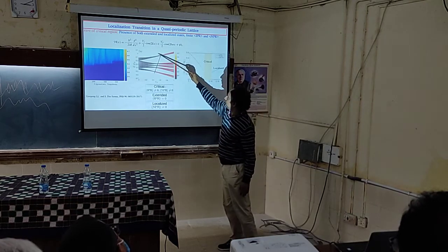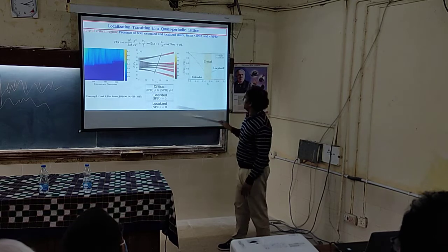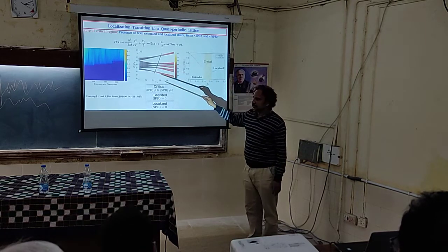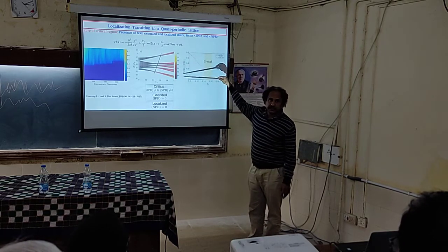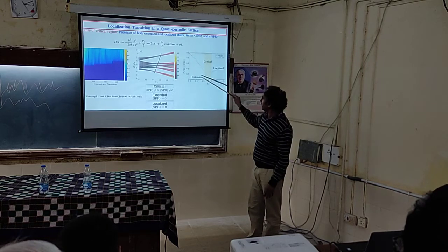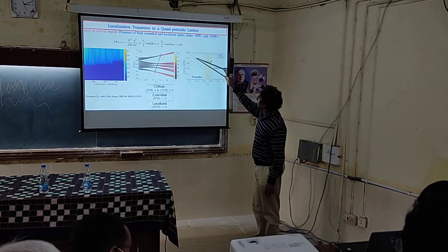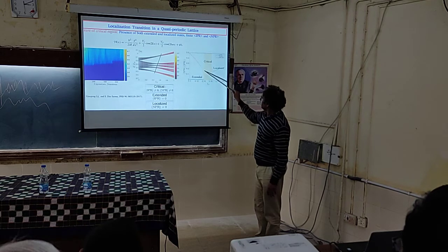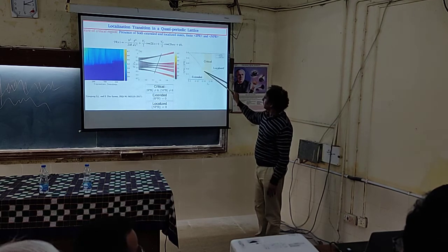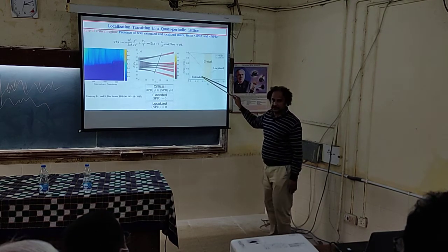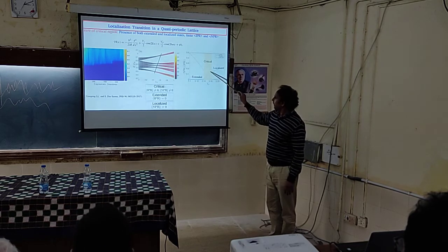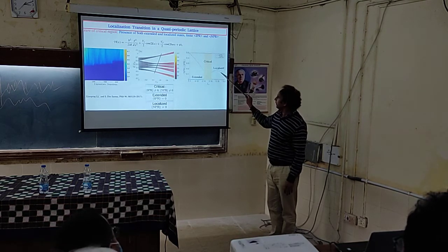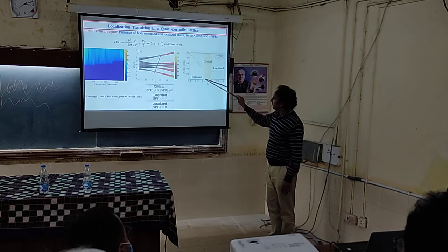So this region from here to here is a critical region, and you can see the signature of the critical region by computing this average participation ratio. So instead of a sharp transition, falling like this, you can see a region here where both these quantities are finite. Both IPR is finite and NPR is finite. And here it is localized, this is extended, and this region is critical.